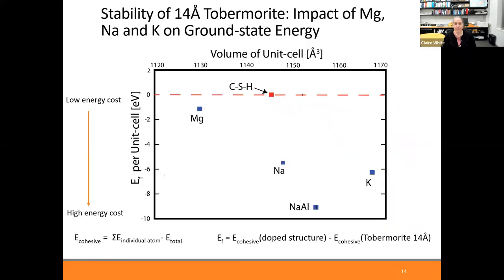So here's a plot, and I'm going to talk you through the results. What we did was for every single structure, we calculated what's known as this cohesive energy, which is the average energy per atom that the system gains by the atoms wanting to bond with each other, as opposed to all of the atoms being separate. So this cohesive energy is a way of knowing how strongly the atoms want to bond together in this system. If the atoms didn't want to bond together, then you would have the energy being zero.